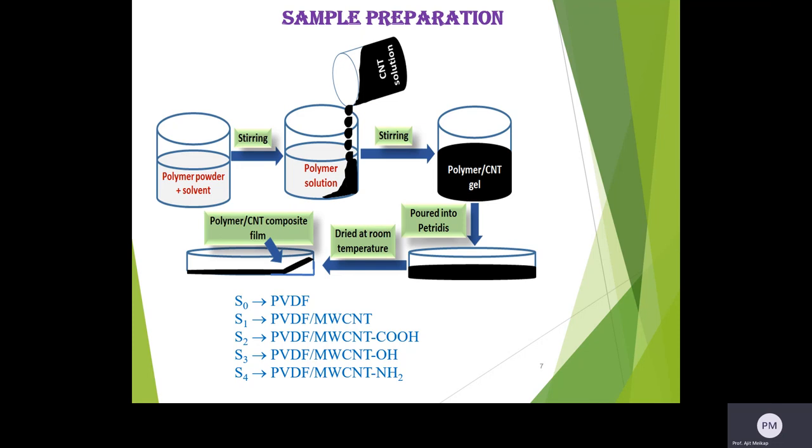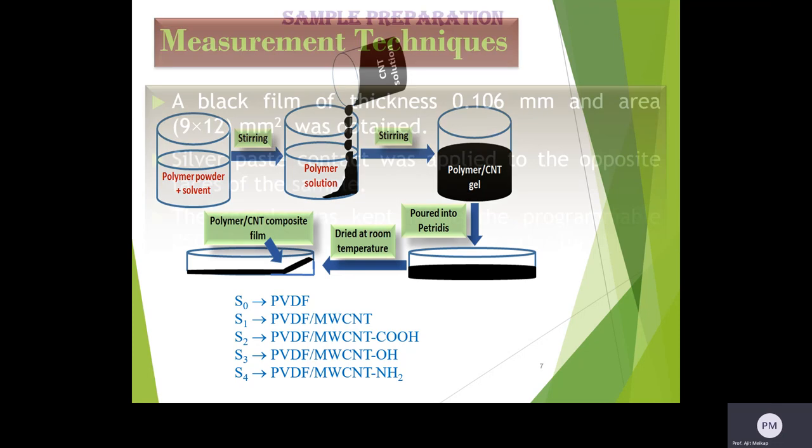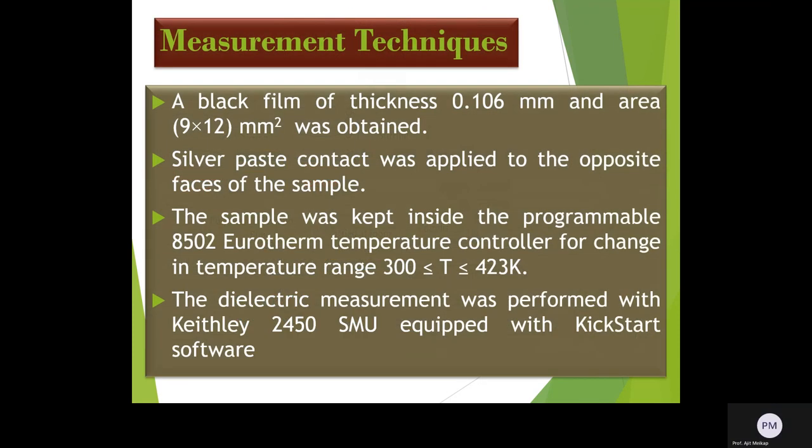The film of thickness 0.106 millimeter and area 9 by 12 millimeter square has been prepared. Silver paste contact was applied to the opposite surfaces of the sample for electrical measurement.